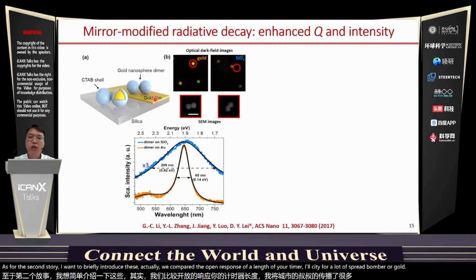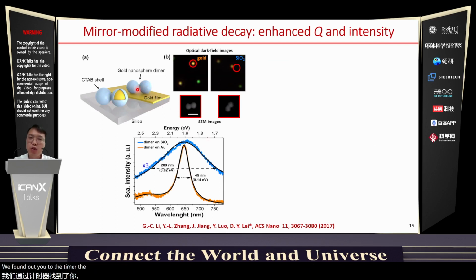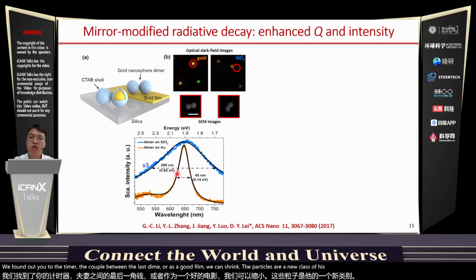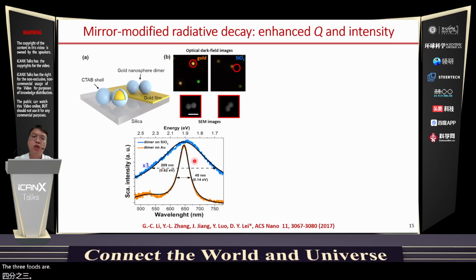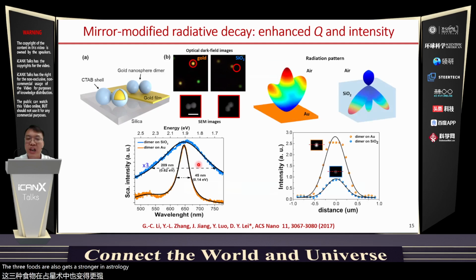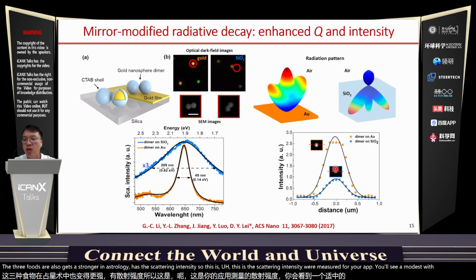We found that due to the coupling between the nanosphere dimer and the gold film, we can shrink the particles' localized surface plasmon resonance by more or less threefold, and also get a strongly enhanced scattering intensity. So this is the scattering intensity measured. You see more or less a threefold enhancement.